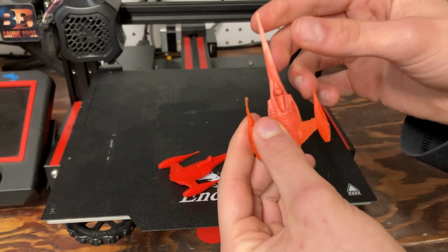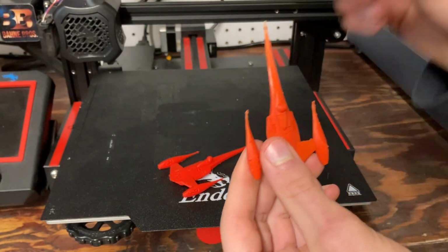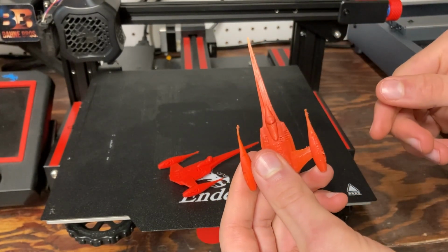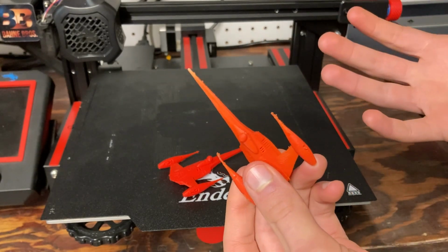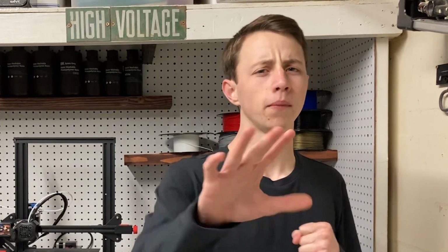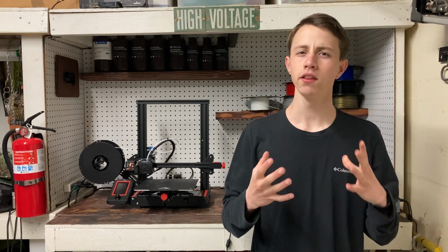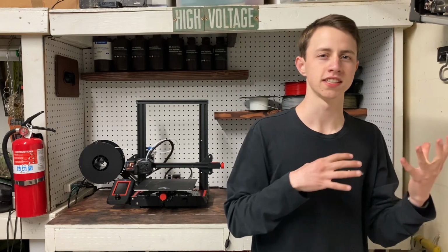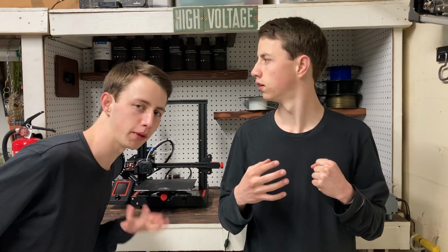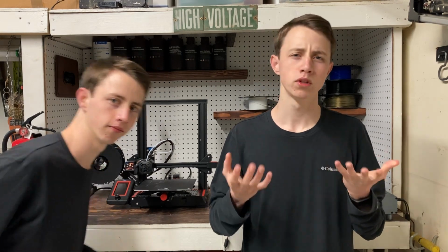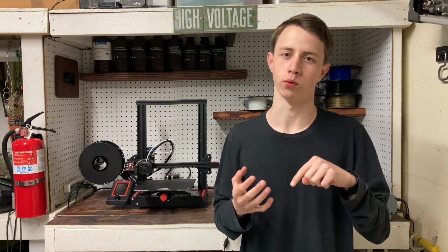Again, PLA is partially soluble in acetone. This solubility decreases with crystallinity and molecular weight, and the natural fillers added to the PLA filament here don't help either. But thankfully, not all degradations of PLA are as anticlimactic as that. In fact, because PLA breaks down into products that aren't toxic in the human body, PLA is one of the most promising polymers for use in the biomedical field. PLA degrades in the human body over the course of 6 months to 2 years. This rate can be adjusted by changing PLA's crystallinity, which makes it useful for applications like this one.